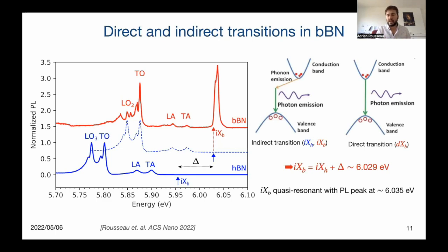The typical intrinsic luminescence spectrum of hexagonal boron nitride is represented here by the blue spectrum. By shifting the spectrum by 74 millielectron volt, we observe a clear correspondence of this line with the lines observed below 6 electron volt in the bulk boron nitride (bBN) spectrum. Then we can conclude that the series of lines below 6 electron volts are associated with phonon-assisted indirect transitions in bulk boron nitride (bBN). And we can then extract the energy of the indirect exciton in bulk boron nitride (bBN), which is around 6.029 electron volt.